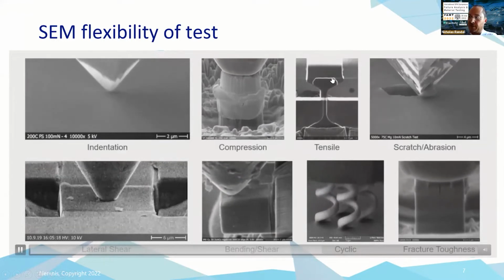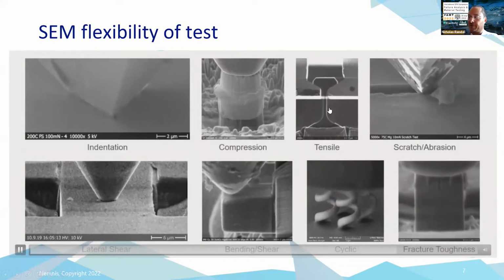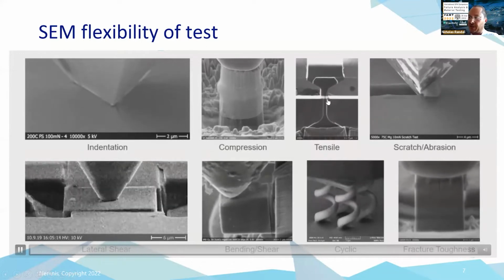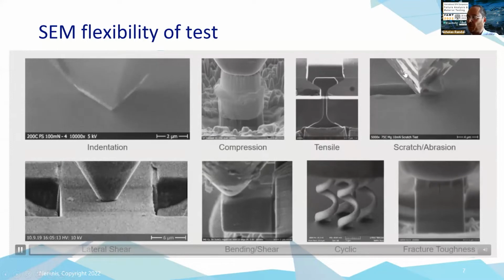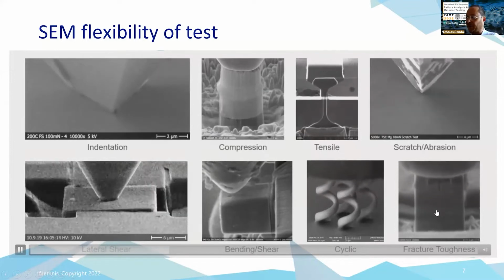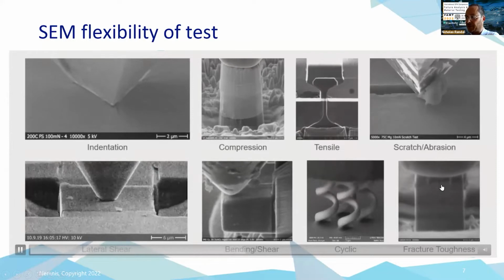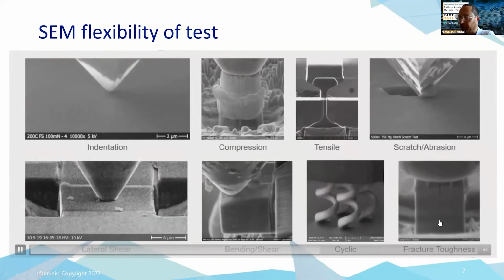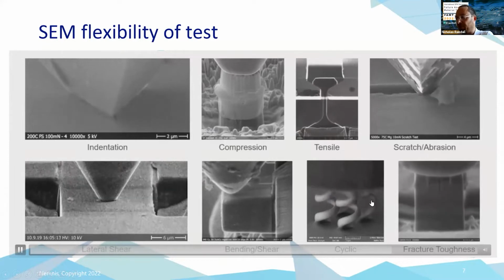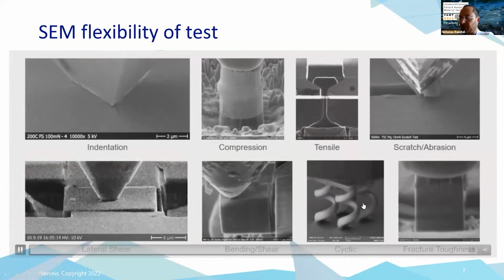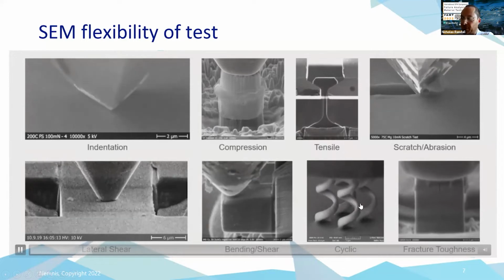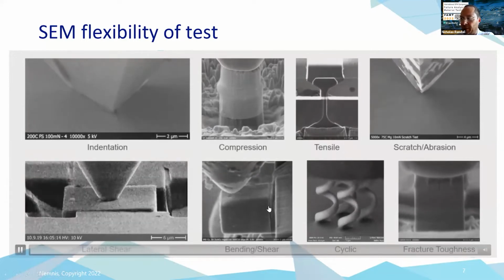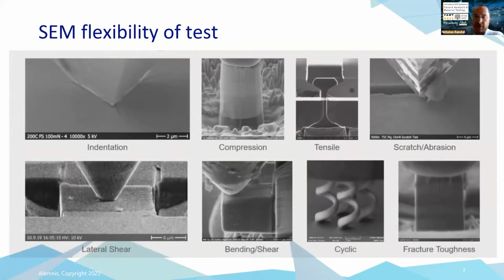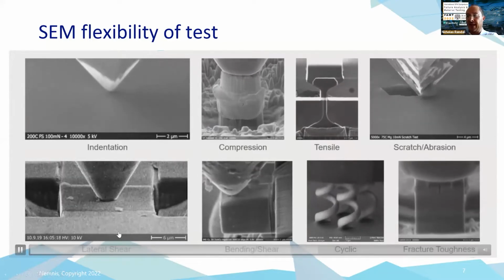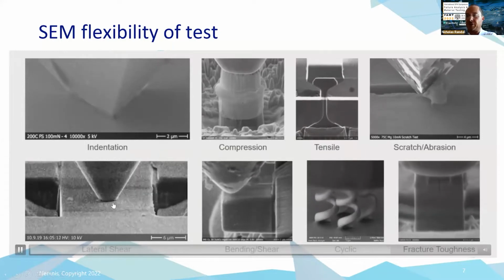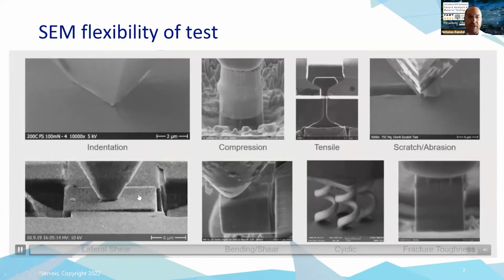We can use the system in tension as well as in compression. So we can FIB very small tensile specimens with gauge widths of a few microns. We can do scratch testing. Down here, we've got a pillar with a pre-crack, so we can actually drive cracks in the uniaxial direction. This is 3D printed small structures. These are springs being tested, but could have application in semiconductor as well. Beam bending, often coupled with EBSD, so we can look at dislocation movements, and lateral testing, almost tribology. So a wide range of test techniques can be used.